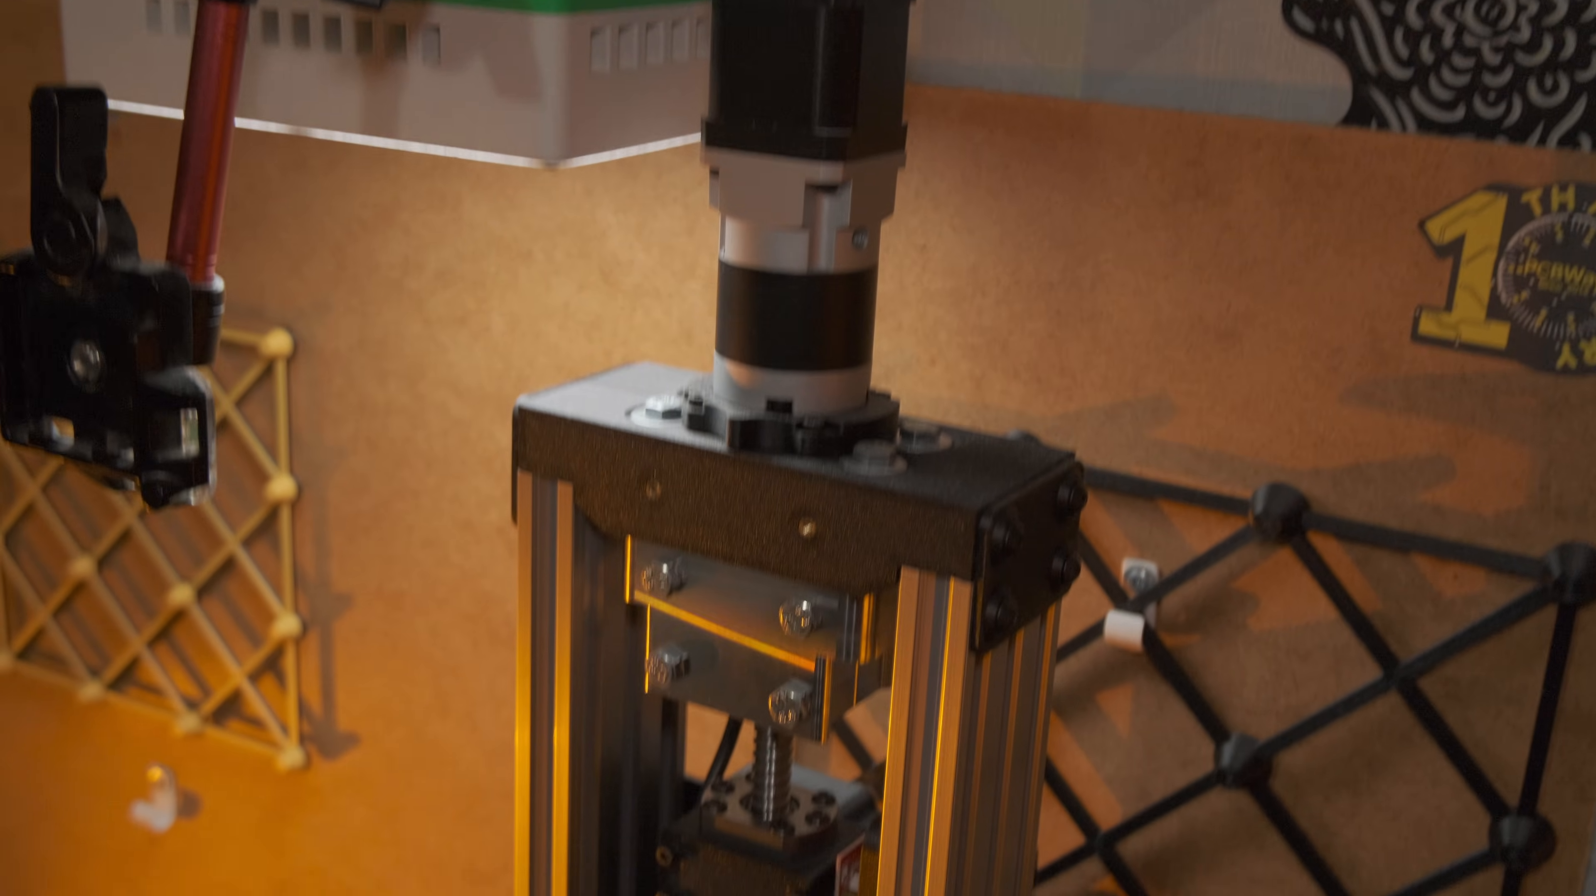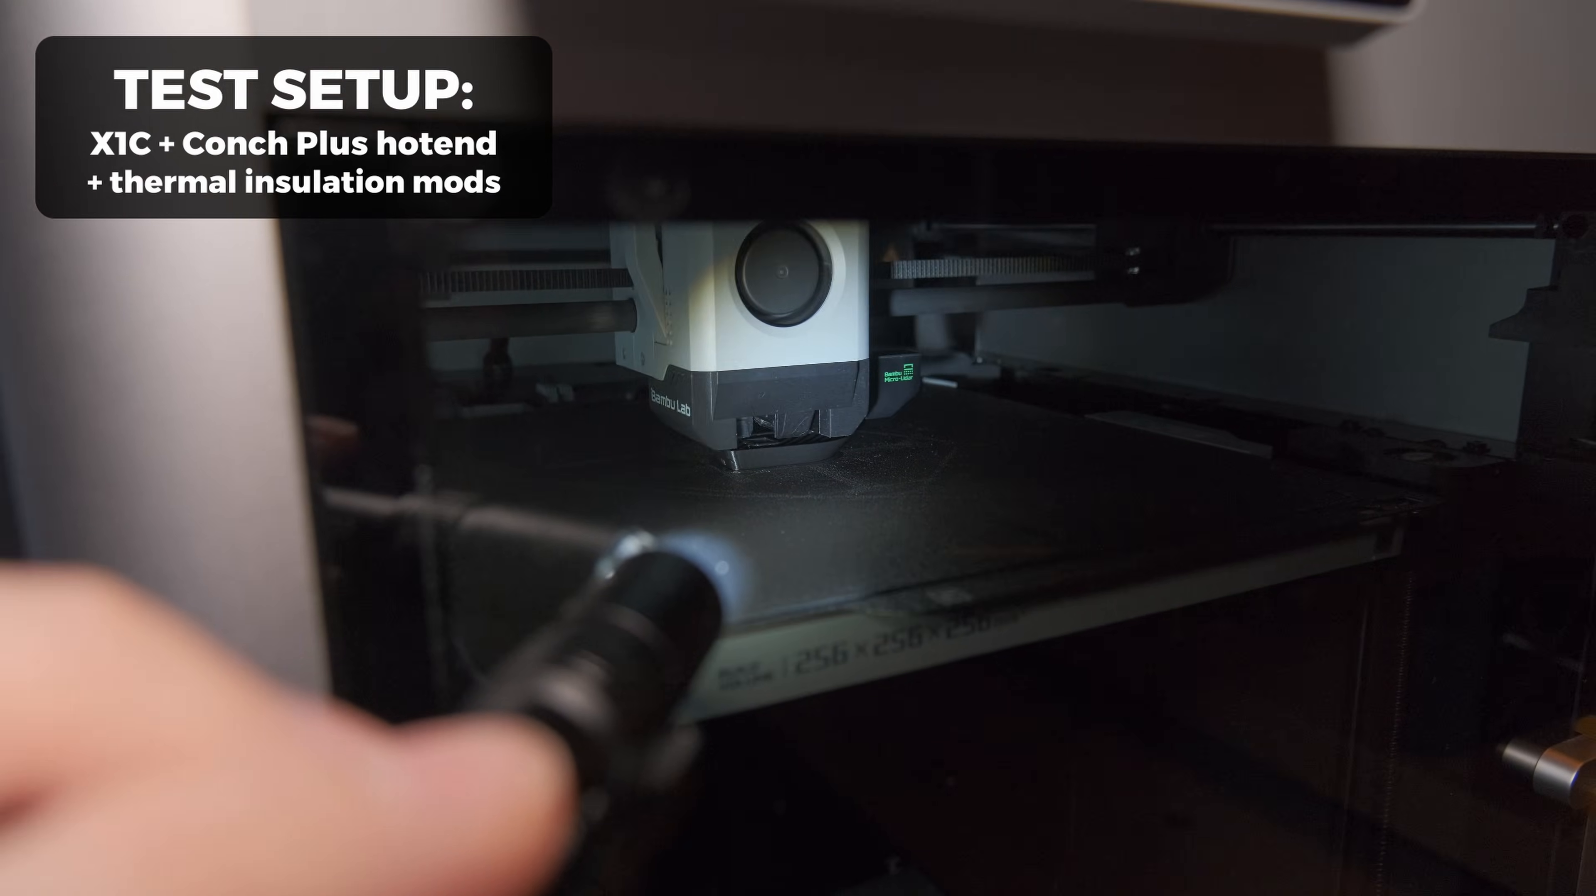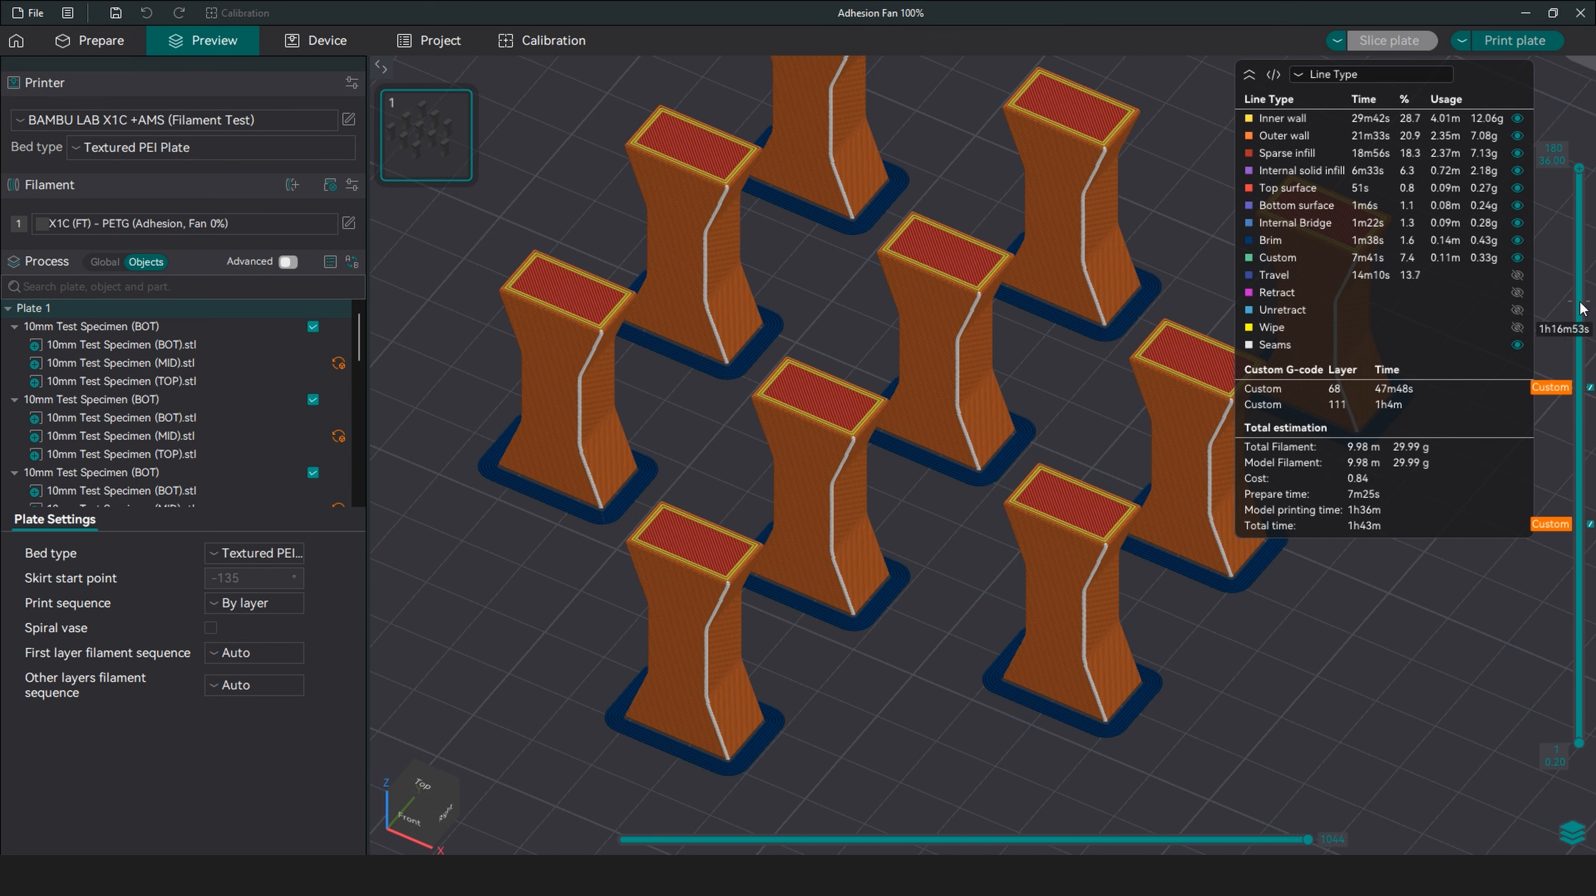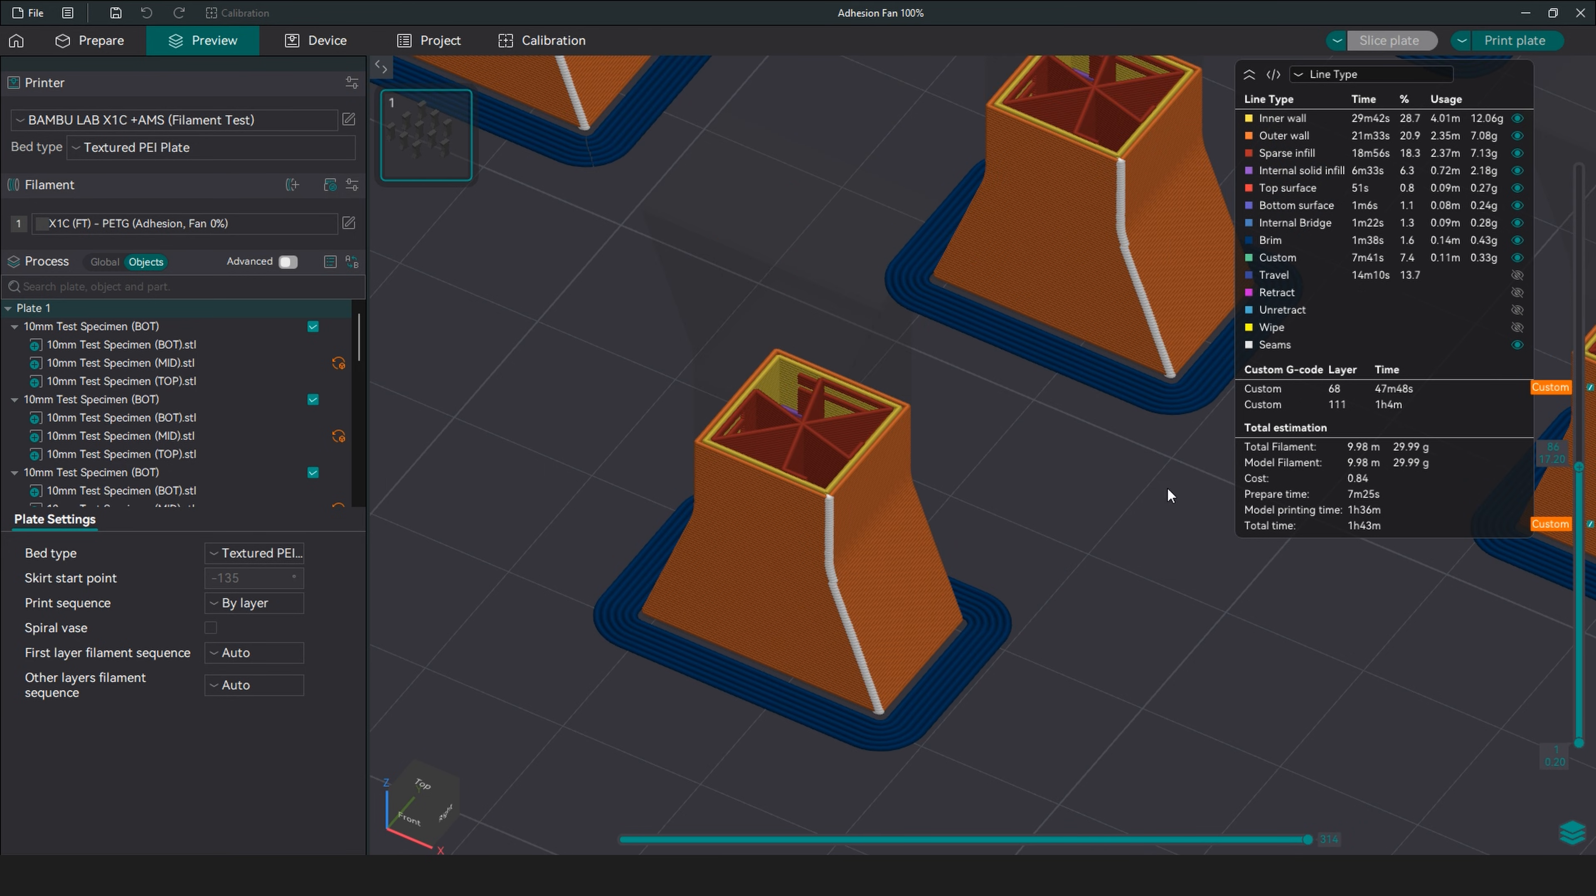With the machine assembled and a couple of tests done, I was thrilled and could proceed with the testing. I always print PETG enclosed, so during all my testing, the chamber temperatures were at 40 degrees Celsius. I designed the test samples to be representative of real prints. They have thick top and bottom sections of three walls and two in the middle for the consistent breaking points.